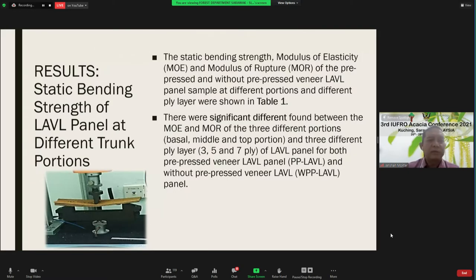So as a result, from the static bending strength of LVL panels at different trunk portions in this research, the basal portion and middle portion LVL show higher mechanical properties than the top portion LVL, for both pre-press and without pre-press veneer, in the MOE and MOR for the static bending test, and also the compression strength. The top portion LVL panel has lower strength due to the large amount of crown form with shorter fiber and lower specific gravity than the basal portion